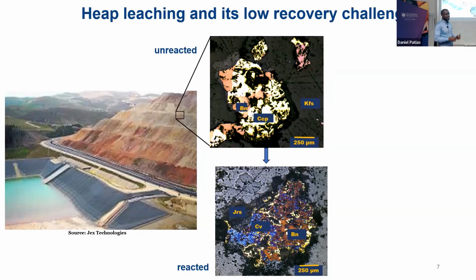After leaching for say 30 days, in our case, you have transformation of phases and development of new phases. So what we are seeing is, first, a darker material around the rims of your copper sulfide mineral, identified as jarosite. Then you have a bluish mineral, which wasn't there initially, but then it's forming.